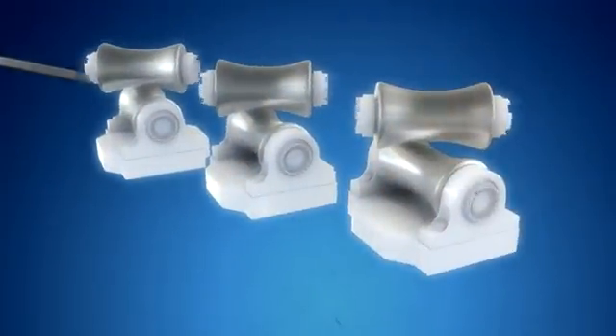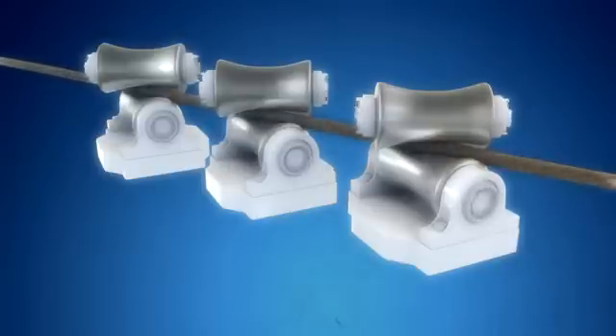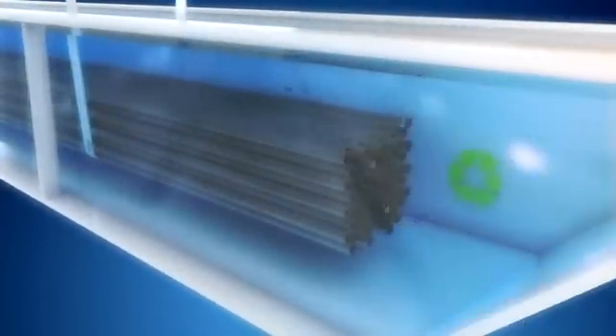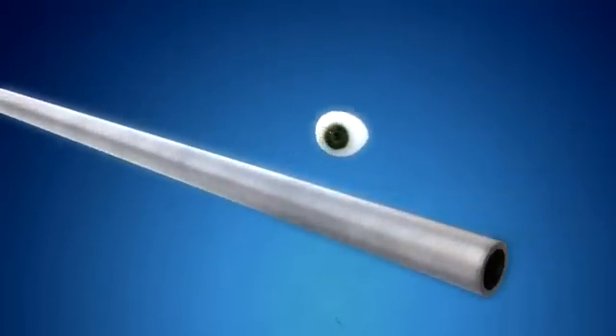The extruded tubes are rapidly straightened and pickled in acid to remove glass and metal oxides. After deburring, dimensional checking and inspection, the tubes are ready for final production.